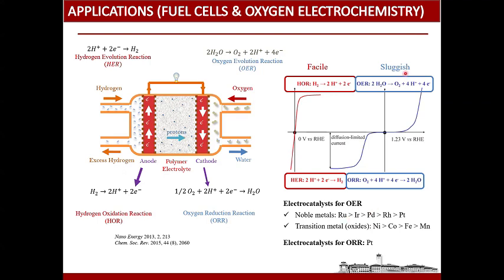Controlling these reactions is also not easy. The ORR reaction is quite sluggish. The OER reaction is also quite sluggish. So we need to control the different steps of these reactions in order to increase the efficiency. The hydrogen evolution reaction is quite straightforward, but still platinum is the most efficient catalyst for it. So we need to find some ways or some new materials in order to decrease the use of these noble metals, or decrease the amount of noble metals in the catalyst, or maybe we should get rid of these noble metals and use transition metals, which are much cheaper and much more abundant in nature.